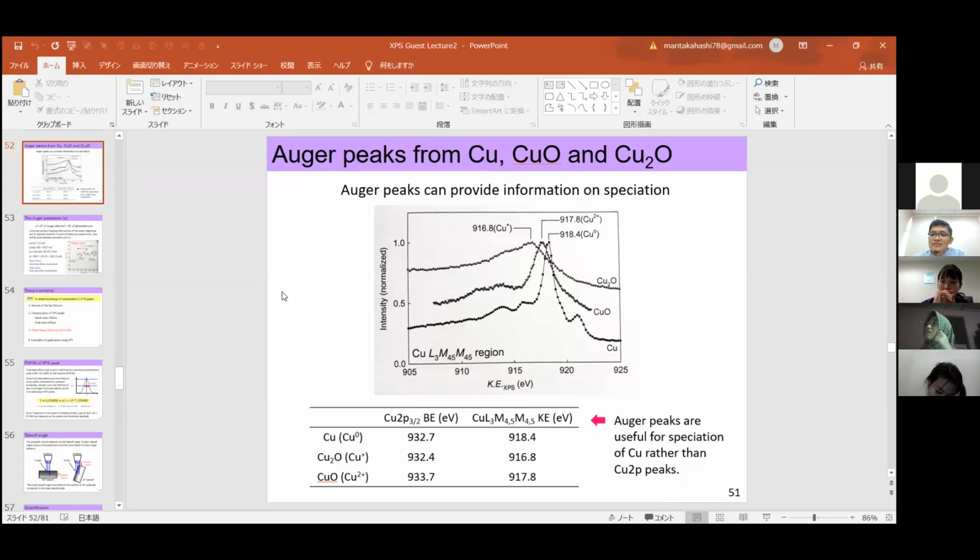So removing only the Auger electron signals in the region which has your main photoelectron peak is difficult. In that case, you may want to check a different position for the element of interest, for example, another 3d or 1s orbital, which doesn't overlap with Auger electrons.